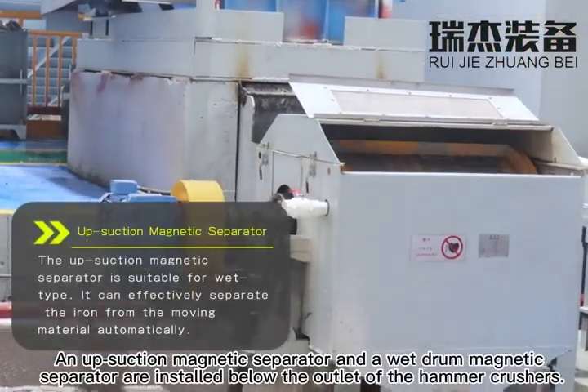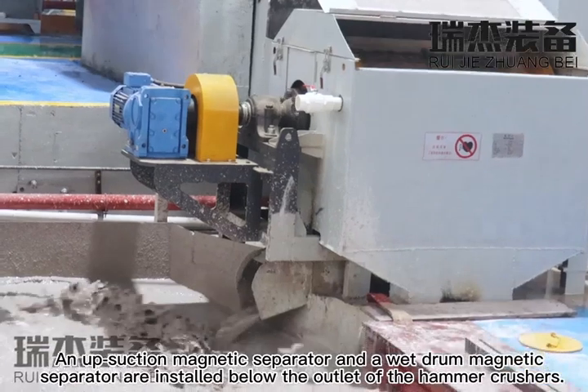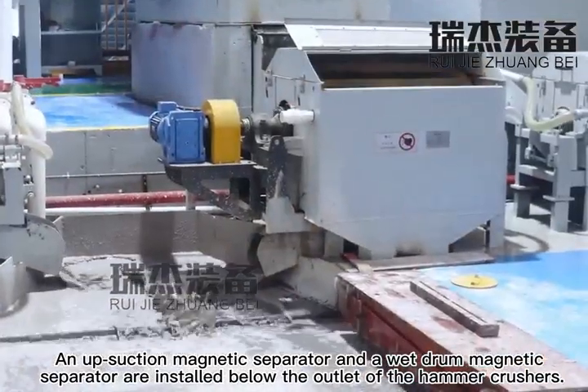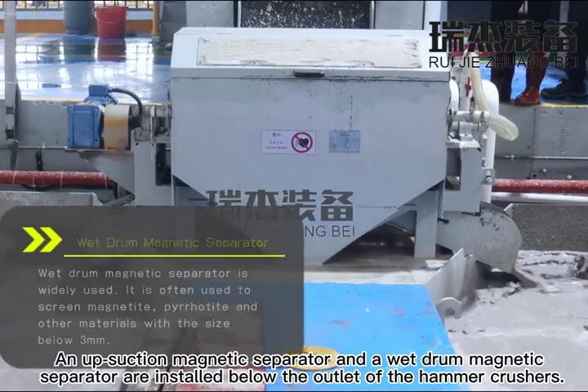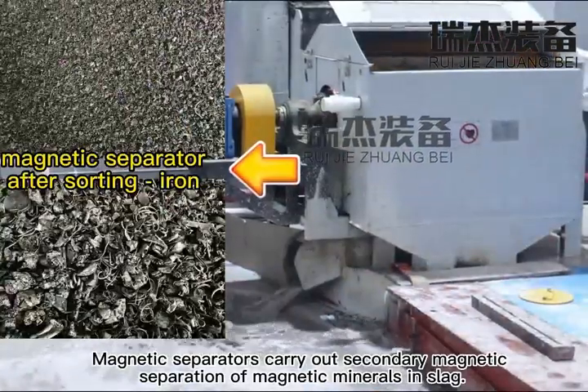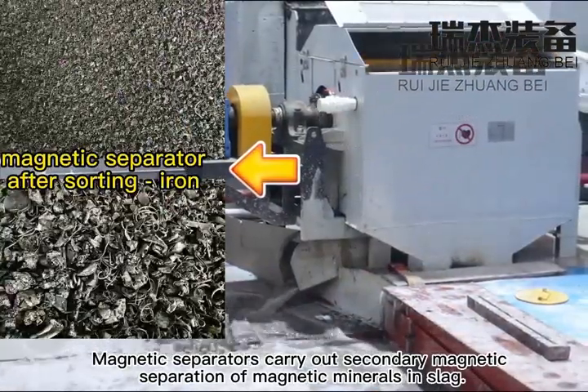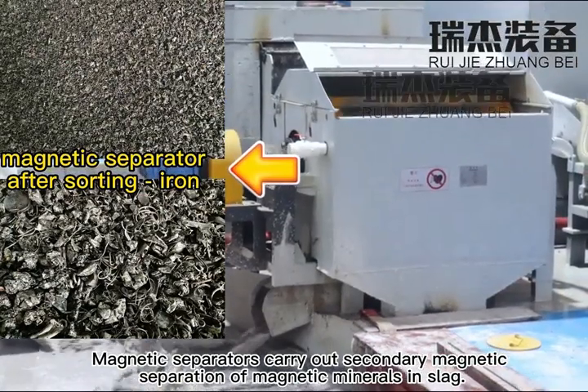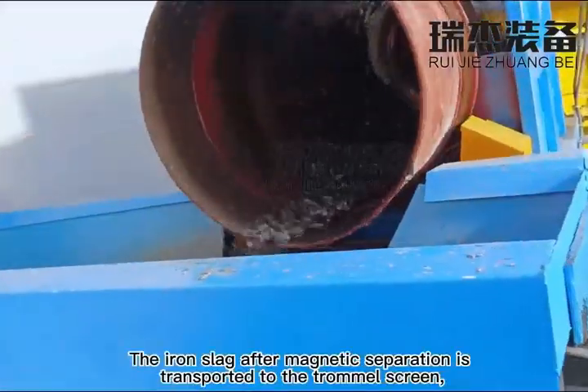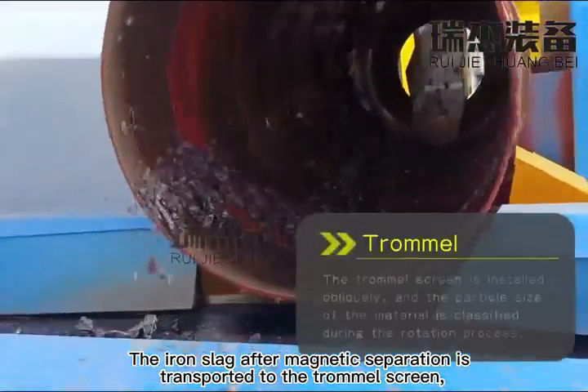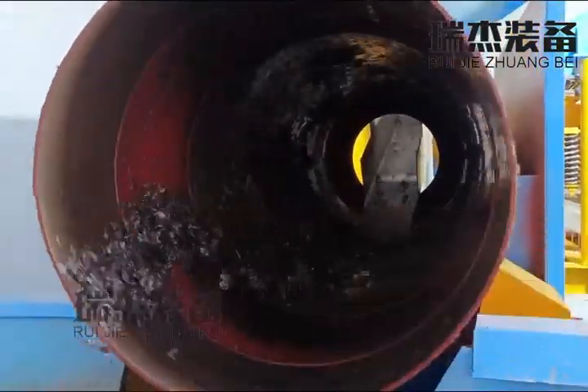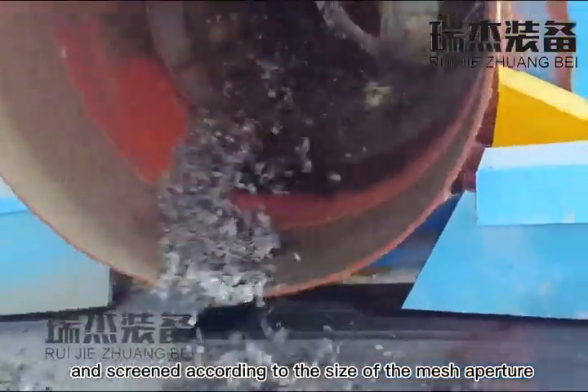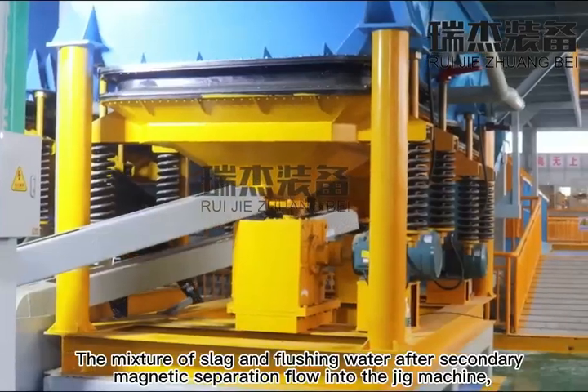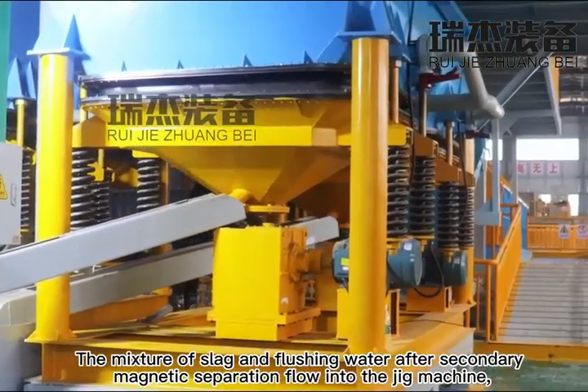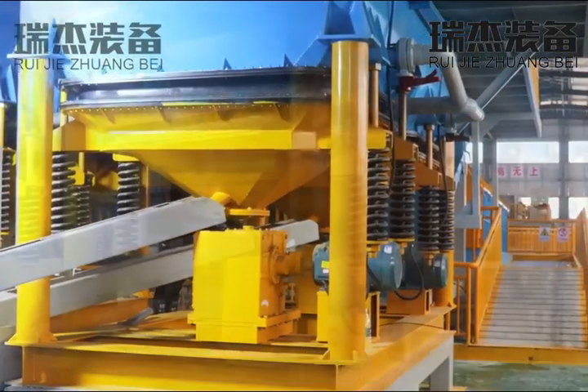An up-suction magnetic separator and a wet drum magnetic separator are installed below the outlet of the hammer crushers. Magnetic separators carry out secondary magnetic separation of magnetic minerals in slag. The iron slag after magnetic separation is transported to the trommel screen and screened according to the size of the mesh aperture.